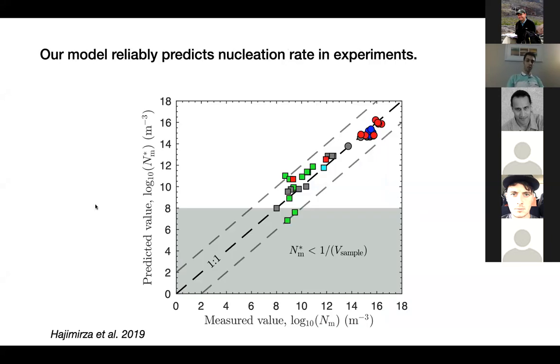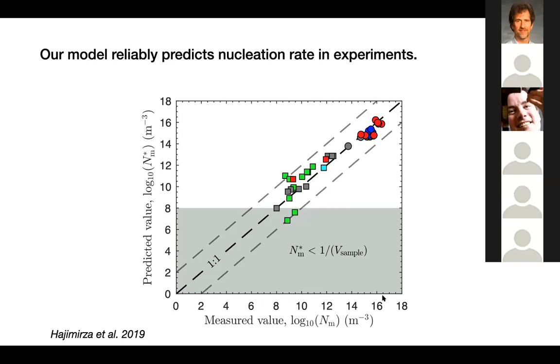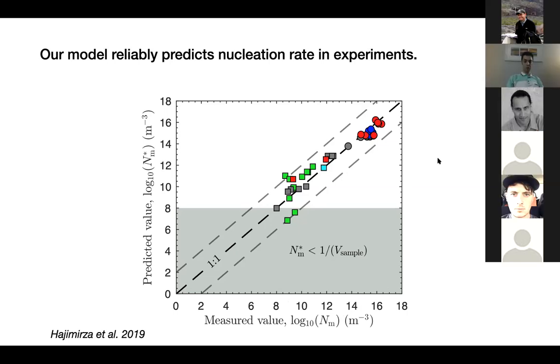Here I'm showing the comparison of bubble number density predicted by our model versus observed in experiments on the x-axis. Our experiments produced bubble number densities that vary over 8 orders of magnitude, from 10 to the 8 to 10 to the 16 bubbles per cubic meter of melt. Our model reliably predicts these bubble number densities over the entire range with less than 1 order of magnitude error on average for all 45 experiments, suggesting our model can reliably predict nucleation rate.